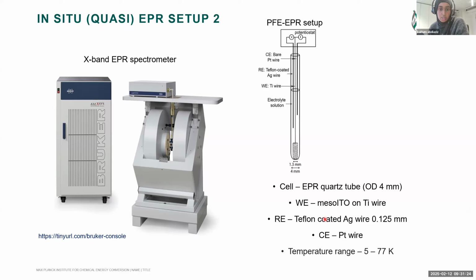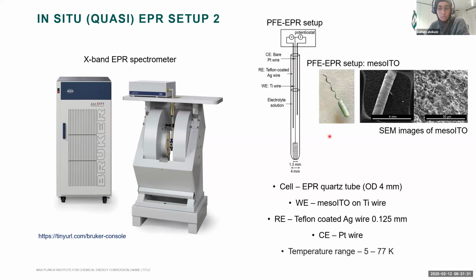So the second system that I will talk about is a setup that I developed in my PhD in Maxie Roessler's group, which is a protein film electrochemical EPR, where we immobilize small molecules and proteins onto these homemade electrodes. These are mesoporous ITO, where you can see from SEM that it has a mesoporous structure. The reason we went for this material is because it's highly tunable and you have a very high surface area. And again, similar to my previous system, the temperature range is 5 to 77 Kelvin. The reason why we have to work at this temperature is because there's a lot of volume of electrolyte, which at room temperature is not the easiest thing to do. It is doable, but it comes at a cost of distortions in your EPR spectrometer measurement, sorry.